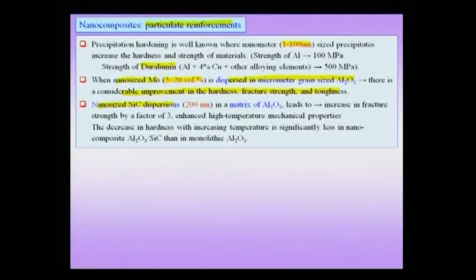Nano size silicon carbide dispersions, again we are talking about silicon carbide in the nanoscale of about 200 nanometers in the same matrix, which is the alumina matrix, also lead to an increase in fracture strength by a factor of 3. So, this is very important, because alumina, being a ceramic, being an oxide, is in a stable state. So, it is resistant to some of those usual things which metals are not resistant to, like corrosion, etc., and it has a good elastic modulus as well. But the problem with ceramics, as you know, is that they are very intolerant to cracks. In other words, they have a poor fracture toughness.